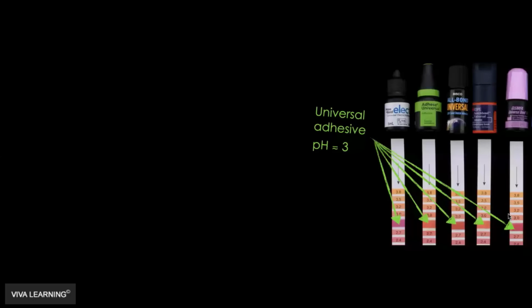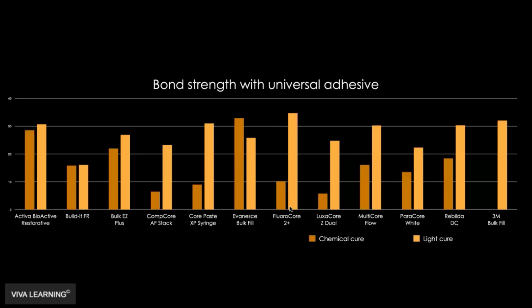So this isn't just an Activa thing. Any of your buildup materials could be inhibited by the acidity of the bonding agent you're using. So we did this test. Again, when I said we didn't do this, Zach Green, who was a resident in our program, did this as his master's project, where he looked at a whole bunch of different dual cure materials and tried to see which ones were inhibited by a universal adhesive, like in this case we're using Scotch Bond Universal.